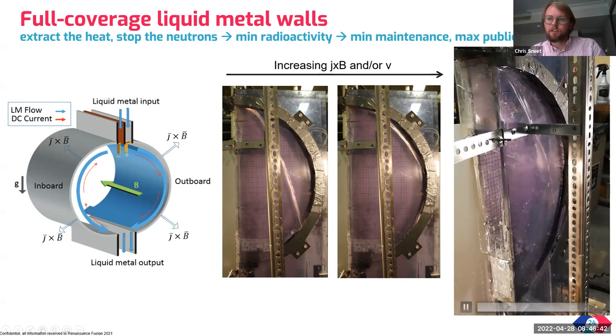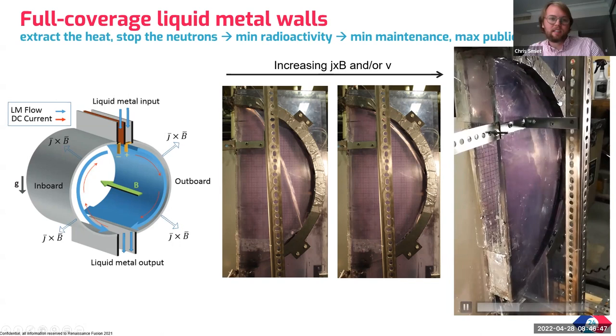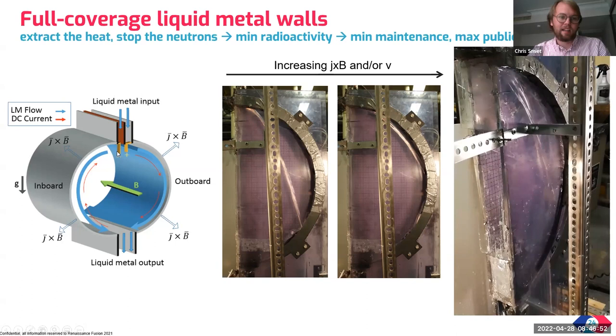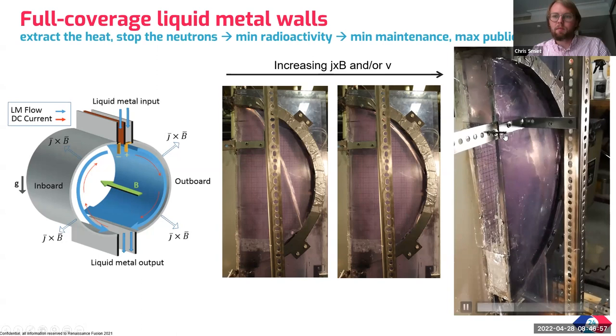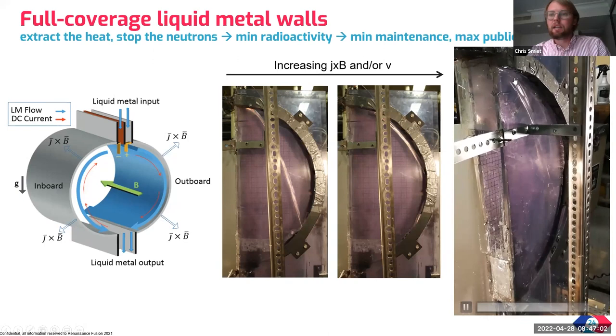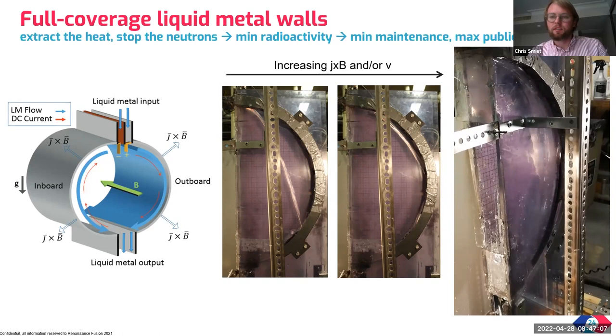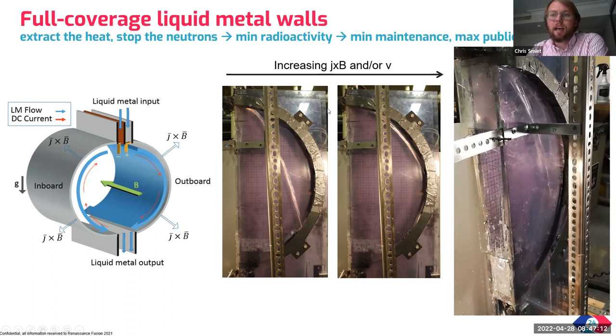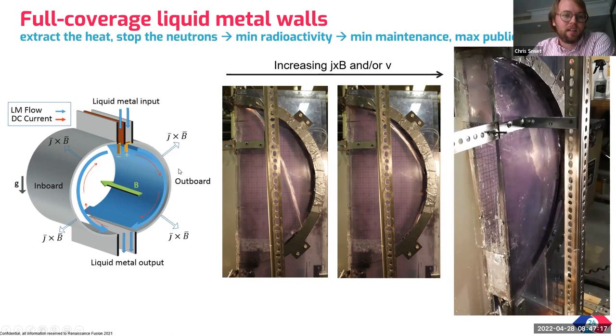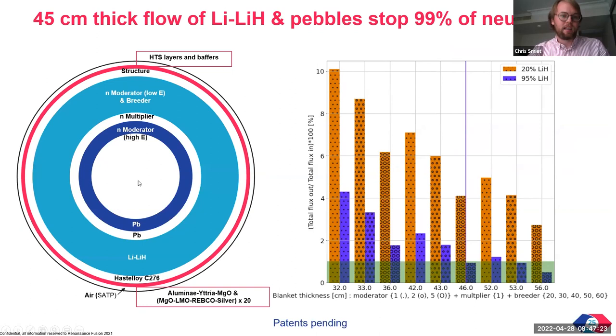So we have this control over the current that we run through the liquid metal, and the magnetic field itself, which is also produced by superconductors and has a very high strength, mostly parallel to the cylinder. With this we can stabilize a relatively thick, mesoscale-thickness liquid metal wall against the inside of the cylinder. Such a liquid metal wall doesn't deteriorate. It's made of lithium or lithium hydride, and it can absorb the neutrons before they even reach the superconductor on the outside of the cylinder. We did some studies on scaling the thickness, some Monte Carlo neutronic simulations, where we look at the effect of different thicknesses of lithium hydride at different concentrations of lithium and hydride.